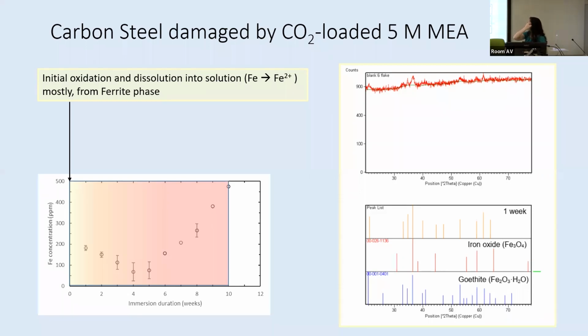So in the graph you see on the bottom left, you've got what is ICP data. So that's measured iron concentration in solution. So we're not talking about anything that's precipitated out. This is all dissolved iron content. And you can see in that very early yellow region, that's where we have that initial oxidation of the iron, and that translation of iron to iron 2+ into the solution. And that's coming from that ferrite phase.